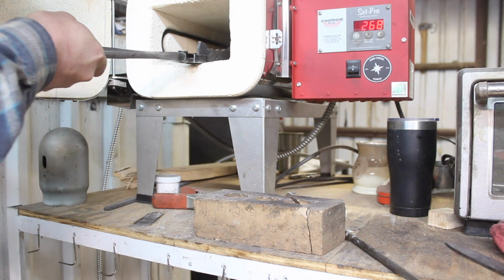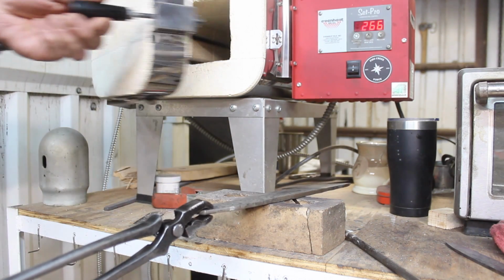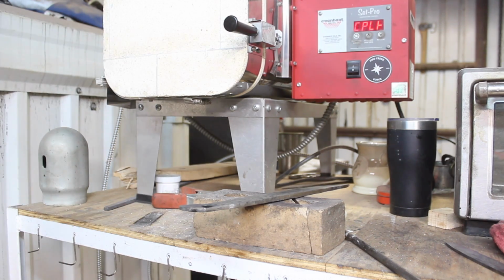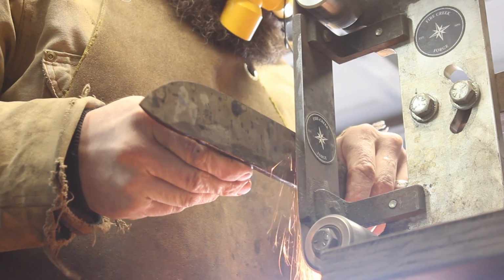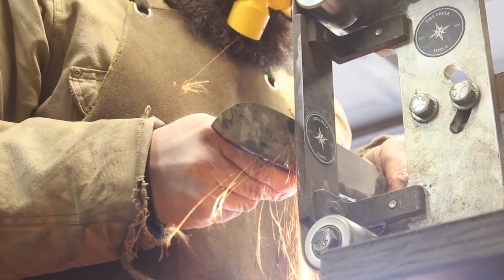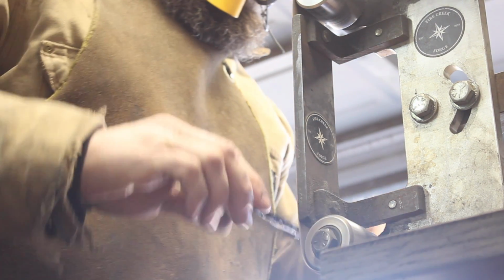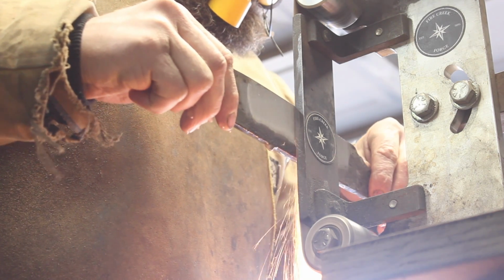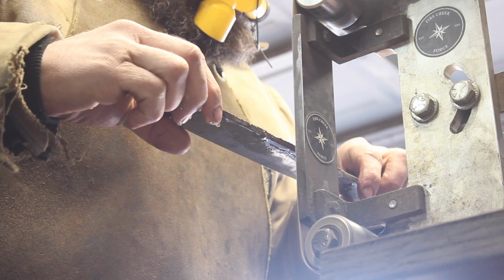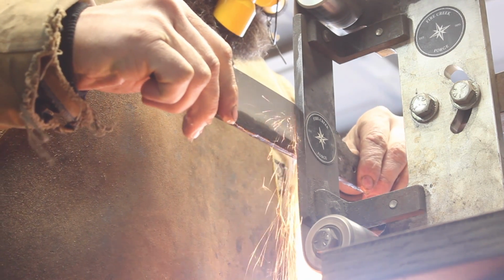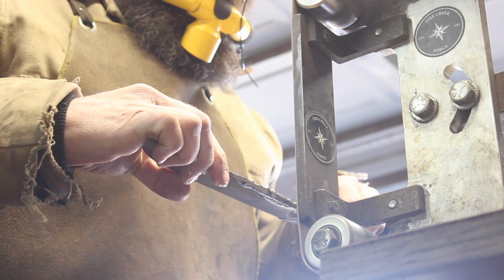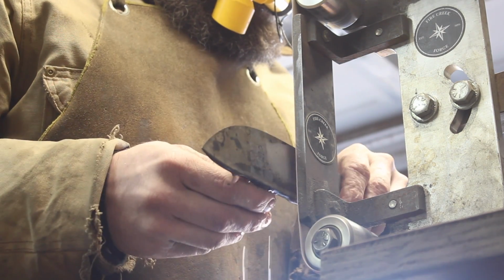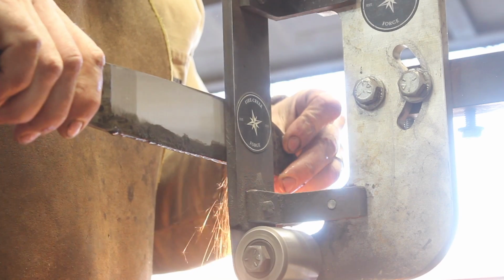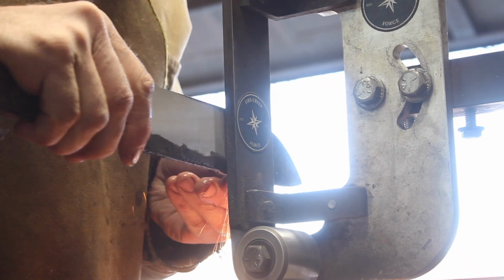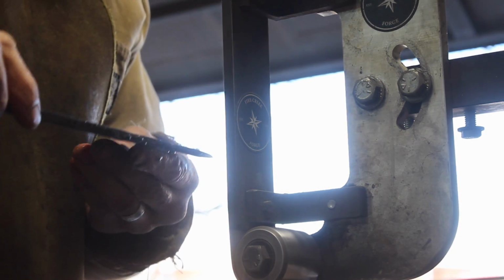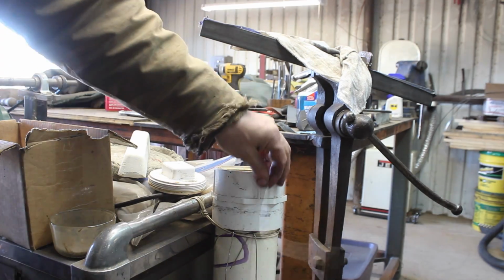Okay, so here we are the next morning, and the knife is fully tempered, twice for 2 hours each time, actually. Now we are ready to do the finish grind on this blade. We still have quite a bit of material to remove, even though we did a rough grind on it. On any pattern welded steel or Damascus steel blade, you're always going to want to remove the outer layer of the steel everywhere on the blade, because you want to finish that surface to an appropriate level that you can then etch in your ferric chloride or acid, depending on what you're using, and reveal the pattern.